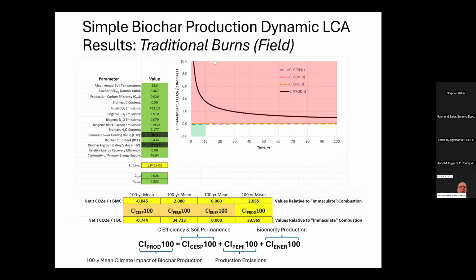So on the left here in the green are the parameters that we work with, and we assume a soil temperature for the stability of the biochar, because that's temperature dependent, depending on the soil temperature as to how long it sticks around for. It's a crude analysis, but it's a valuable one. So I picked the temperature for the Usal Forest, since that's where the biomass was harvested. So the annual temperature there is around 13 degrees Celsius.